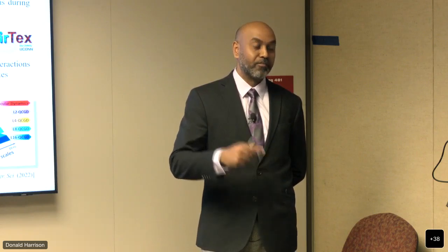Take single crystal diamond. You predict the phase and you take it up to a pressure well above its transition, the BC8 phase. If the potential is fit to predict that phase transformation above a certain pressure and we drive it to those pressures, we will see it. So it comes down to the potential. Yes, it does. Our capabilities are limited by the potential, in that sense.